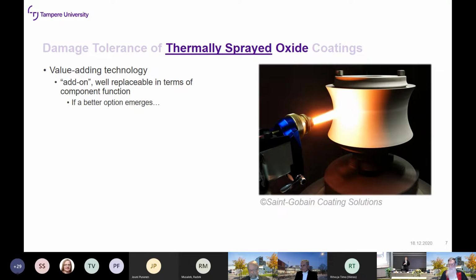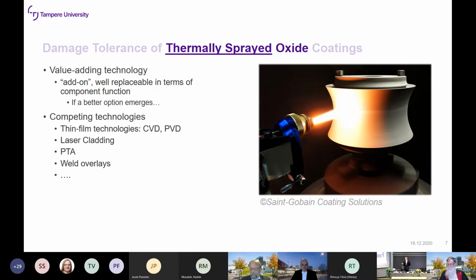Now, thermal spraying itself is a value-adding technology, meaning that in most cases, the components would work without a coating quite well, probably a bit shorter time, but they would work. And by applying a coating, we can increase the lifetime of the component, maybe 5 times, maybe 10 times, maybe 2 times. And in some cases, it's not worth it to apply a coating. But thermal spraying by itself usually can be replaced if there is a better option from, for example, thinner coatings in thin film technologies such as chemical vapor deposition or physical vapor deposition, or thicker coatings, clads from laser cladding, PTA or welding. So it is really a niche technology between thin coatings and thick coatings, and its use is quite niche as well.